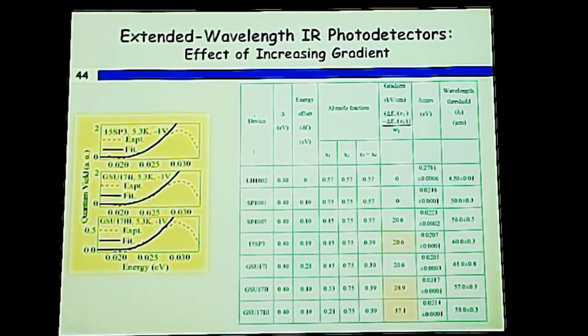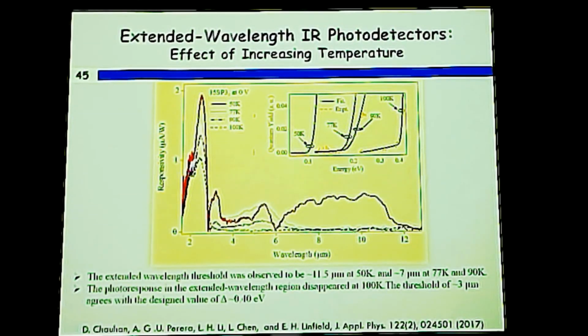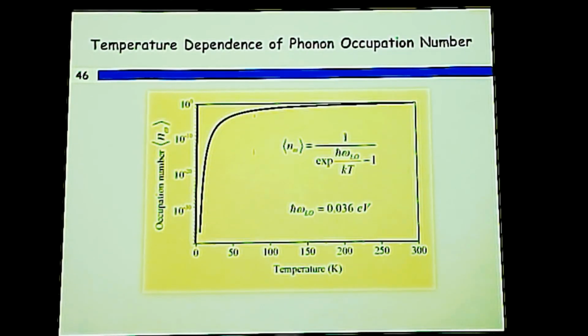So far, all the measurements were carried out at 5.3 Kelvin for the extended wavelength mechanism, but our interest is to develop detectors that operate at high operating temperatures. The extended wavelength mechanism is gone dramatically with the temperature. That is one question. What changes dramatically is the phonon population with the temperature, and for gallium arsenide, the LO phonon energy is 0.036 electron volt, and you see the occupation number from 5 Kelvin to 50 Kelvin or so changes by many orders of magnitude. That is one thing. But again, the question is, why is this related to the extended wavelength mechanism?